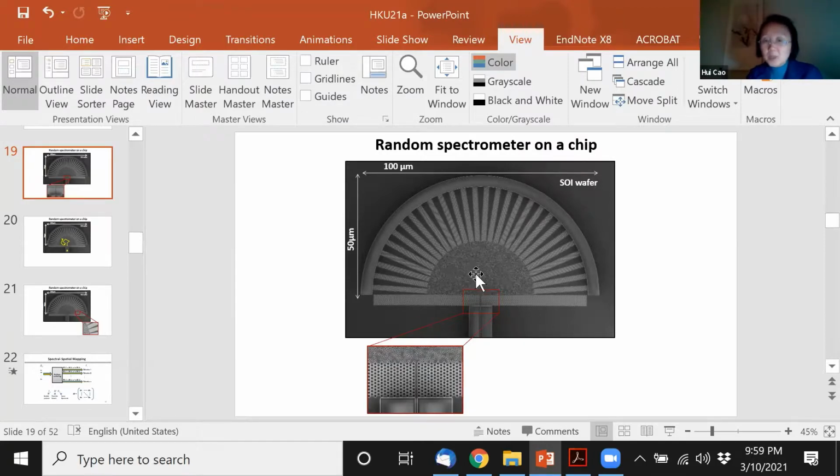That's a very good question. So typically, what do we do? We actually use a dilute, lower density of scatterers here, and very highly random structures there. Just like wall paint, the reflectivity is very high, right? Because it's a random assembly of scatterers. So if we can make a highly disordered structure here, we can replace the photonic crystal with a highly disordered, closely packed structure. That will also have very high reflectivity compared to this region, which has more dilute scatterers. So that can be a broadband confinement.